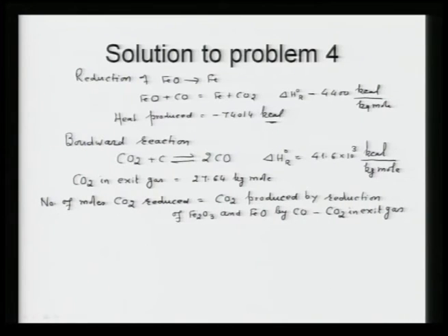That is what is happening. Also, plus that point we always forget, plus CO2 from calcium carbonate. Do not forget this calcium carbonate and its contribution, because this is also giving CO2, and every chance that CO2 may be reduced by the carbon according to the Boudouard reaction. So, this is our balance.